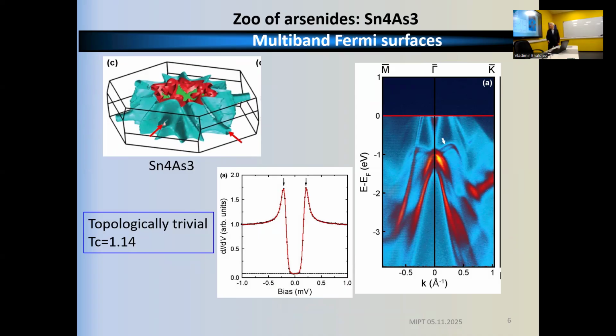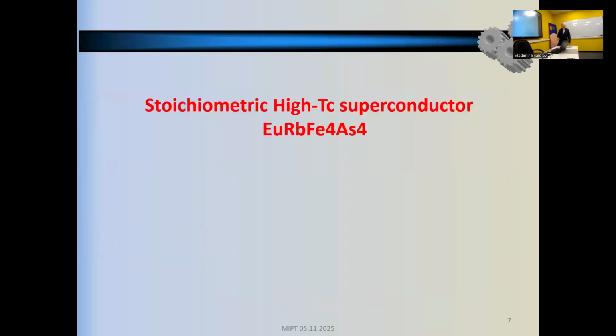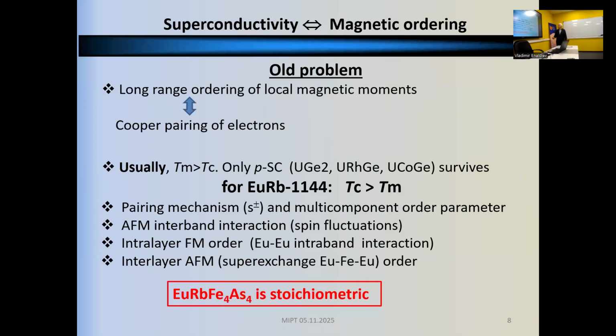So these measurements of the scanning tunnel spectroscopy were done by Peter Weyl, who had STM with the dilution fridge. And finally, we moved to more interesting materials which actually combines the properties of layered semimetals, but because it stacks two layered materials with different ion radius, like europium and rubidium, therefore, it's internally strained, and with no doping, it becomes superconducting.